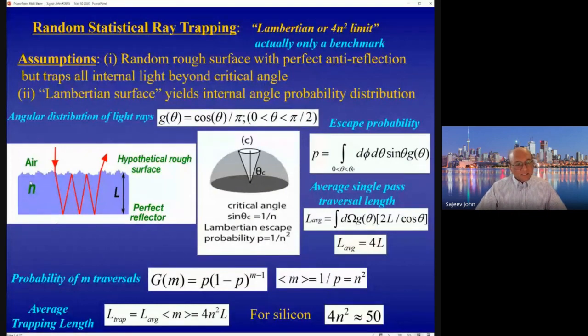And so the idea behind this statistical ray trapping was that instead of having a flat solar cell, perhaps you could create some sort of a random or rough surface so that when light from the sun impinges on it, it would be deflected at some angle relative to the normal, then be reflected off the mirror at the back, come back to the top, and if that angle was sufficiently large, it might bounce back in again by the mechanism of total internal reflection, and thereby increase its path length so that absorption would take place.